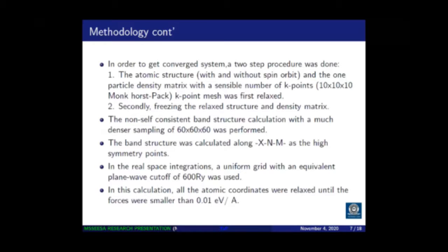Still in methodology, in order to get the converged system, I used a two-step procedure. The first thing, I began with the atomic structure, both with and without spin-orbit coupling, and the one-particle density matrix with a k-point 10 by 10 mesh was first relaxed. And secondly, freezing the relaxed structure and the density matrix.